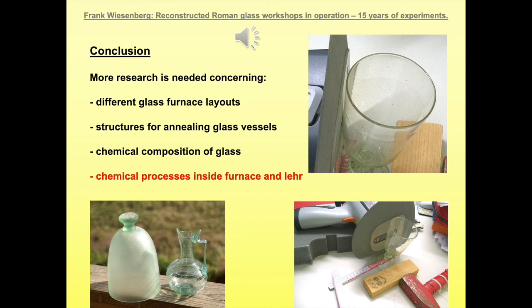We did start to employ a glass dome, as can be seen on the left picture, which did protect the very shiny jug on the right part of the left picture. So the jug was placed inside the glass dome, inside the annealing oven at Welsica, and obviously the dome was affected by the dulling, and the glass jug, which was covered by the dome, was not. So this is very interesting to notice.